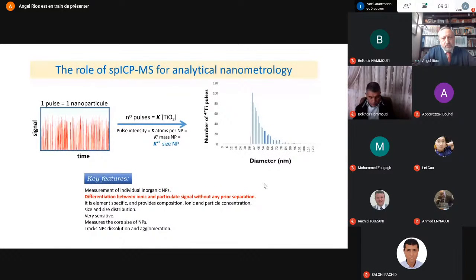I also want to remark on the important role played by ICP-MS spectroscopy, especially in the single particle ICP mode, in order to give information in the general framework of analytical nanometrology. This technique, single particle ICP-MS, provides information about each single particle arriving at the detection system. For instance, every nanoparticle reaching the detector corresponds to one pulse in the recording, and the number of pulses is directly proportional to the concentration of the nanoparticles, and also the intensity of the pulse can be related to the size of the nanoparticle.